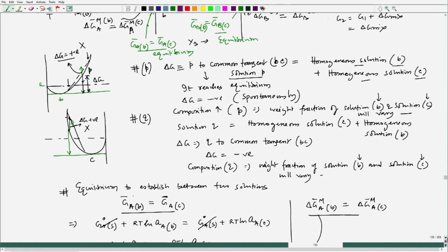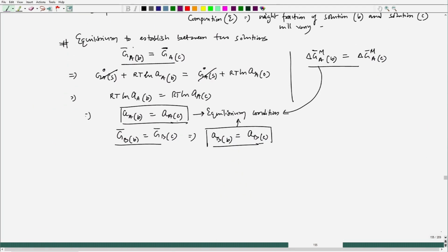This separation of composition happens because delta H mix is highly positive, and it leads to AA type and BB type bonds to form, preferably.